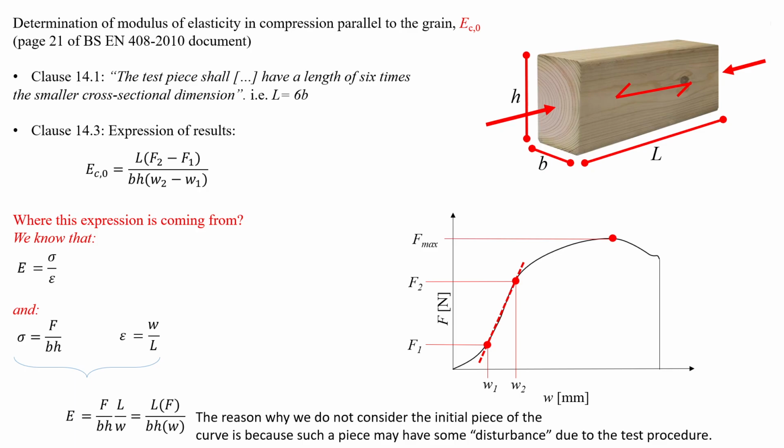If you don't, you will next week, because I'll be teaching it to you in the tutorial. We'll do an R squared fit to make sure it's within 1%, i.e. 0.99 R squared. If it's not as good as that, then you'll have to change these 2 points to make it within that tolerance, and only then will your numbers be valid. Okay. Hence why it's an approximation of 10 and 40%.